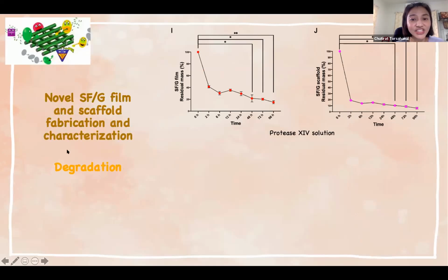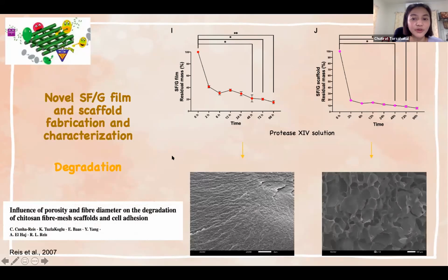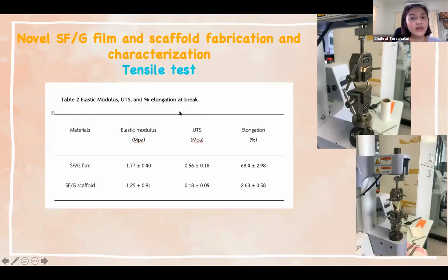And about the degradation of the SFG film and SFG scaffold. From the graph, the SFG scaffold has faster degradation than the SFG film. This is possibly caused by the porosity of the SFG sponge-like scaffold. And the next part is the tensile test. I will analyze the tensile test of the film and sponge-like scaffold by elastic modulus, ultimate tensile strength, and elongation at break.